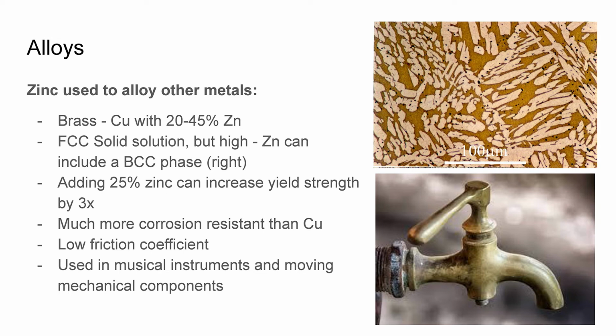on the right. And at really high zinc levels, there's naval brass, which has really good corrosion resistance, and so they actually use it submerged underwater. Uses for brass also include low coefficient of friction applications, like moving mechanical components. So that's why they use it in musical instruments. Because if you have a trumpet, you're blowing moist air through it, and you're moving the valves, and you don't want it to last like half a year. So they make it out of brass.